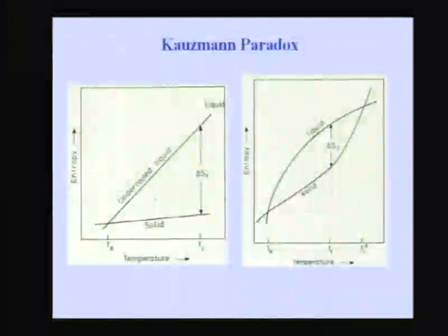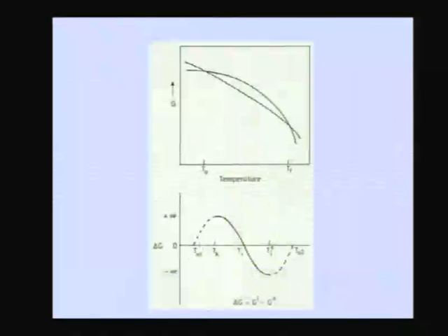So, that is why Cp of the liquid and glass will be different at the melting point, but the entropy of the glass and liquid, enthalpy of the glass and liquid, volume of the glass and liquid, they are all the same at the melting point. That is what one of the parameters we are showing here, which is entropy, and one can show the same thing for the enthalpy also. Okay. And you can see that here.